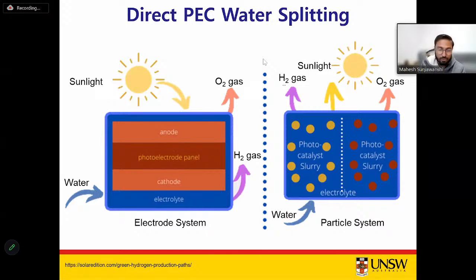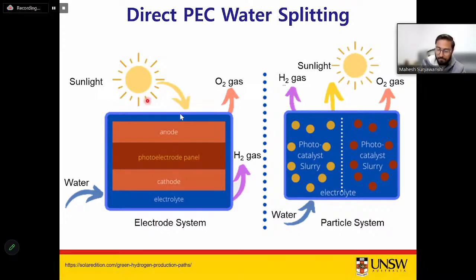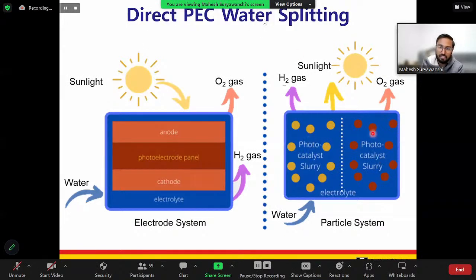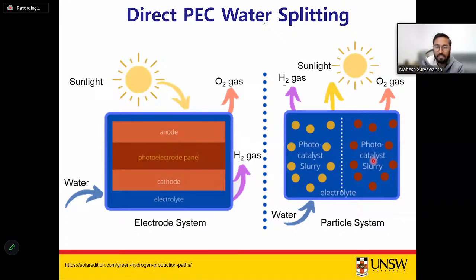So simply, how is hydrogen produced using PEC water splitting? These are simple schematics of the electrode system. This is a thin film electrode system and this is a particle system. The only difference is that we prepare thin films of energy-absorbing materials, put them in the electrolyte or simply water, shine a light, and then there is production of hydrogen and oxygen. But in the particle system, you don't need to prepare an electrolyte. You only need to prepare the photocatalyst, which is a particle suspension, or slurry as we call it, and then dilute it with a water and ethanol mixture and just shine a light on it. This photocatalyst slurry will produce hydrogen if it is a photocathode, and oxygen if it is a photoanode, I mean a p-type or n-type semiconductor.